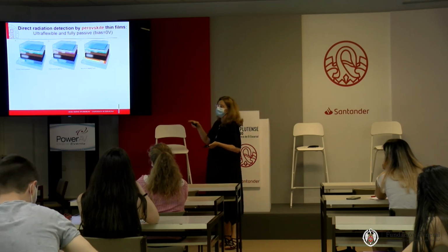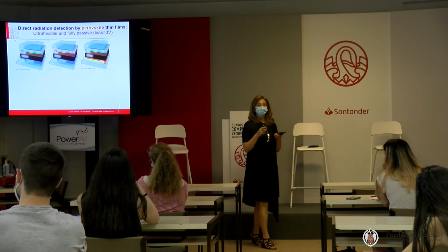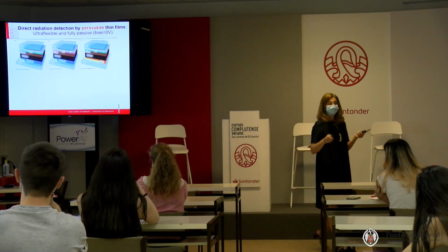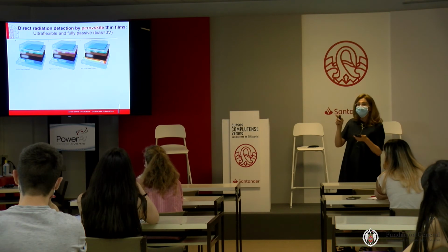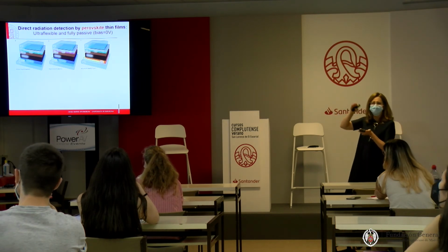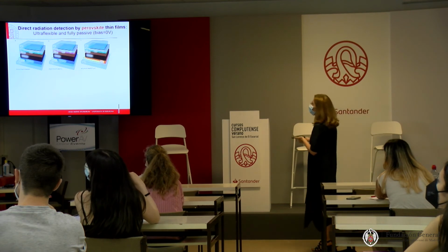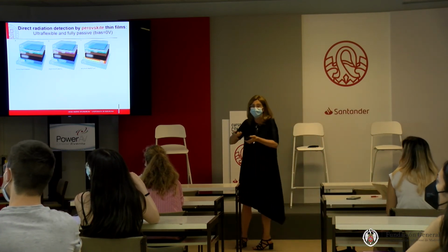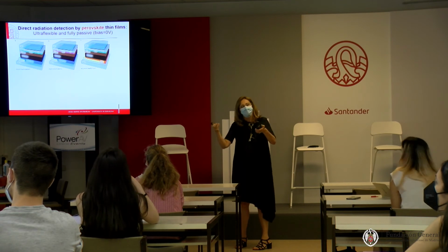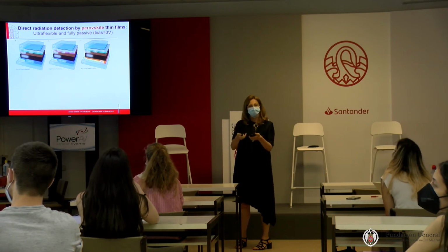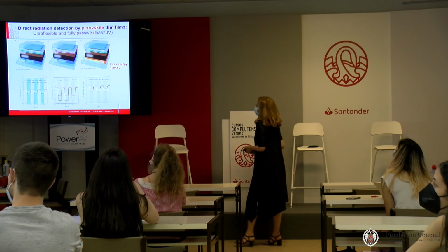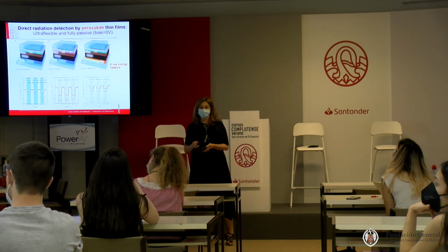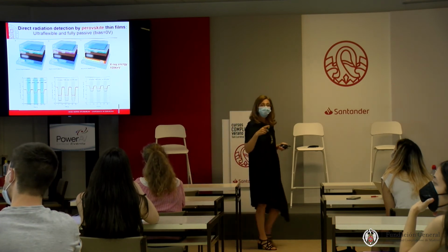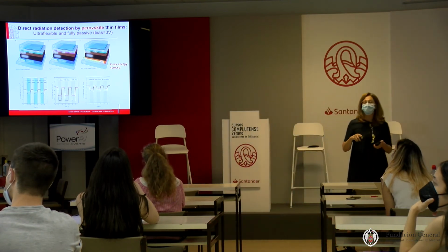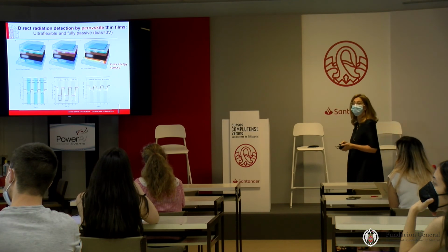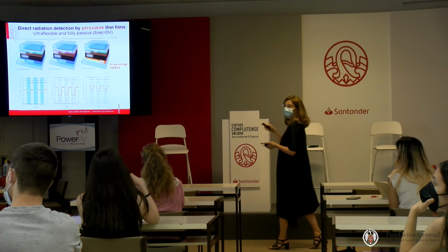Here is an example of three of these structures. You see the perovskite layer is the same in all of them, but what changes are the very thin, few nanometer thick interlayers that are used as electrodes, the hole transport layer or electron transport layer that collect the holes or the electrons, respectively, photogenerated inside the perovskite. You see that all these three work very well. Look at the nice on-off response to an on-off X-ray beam. You see clearly when the beam is on and off. The response is sharp, fast, and reproducible.